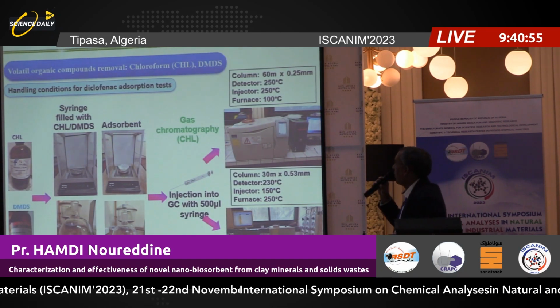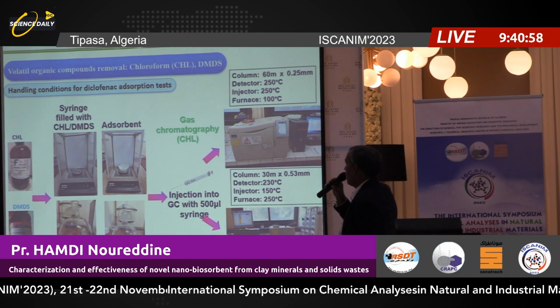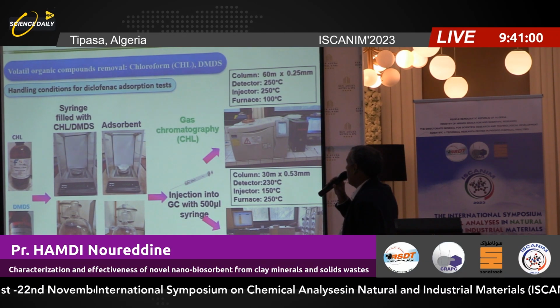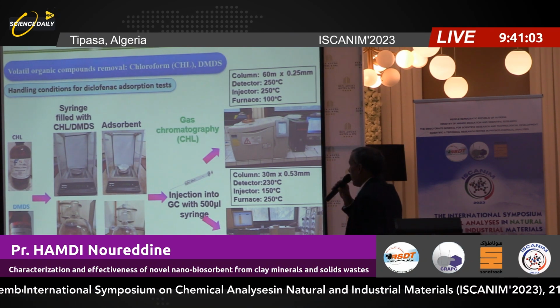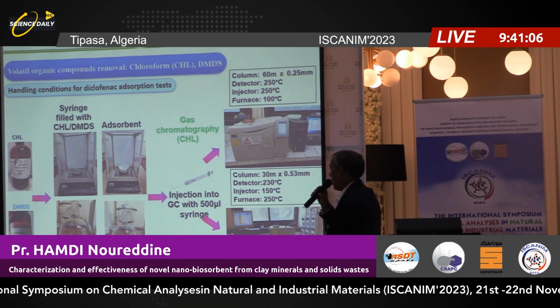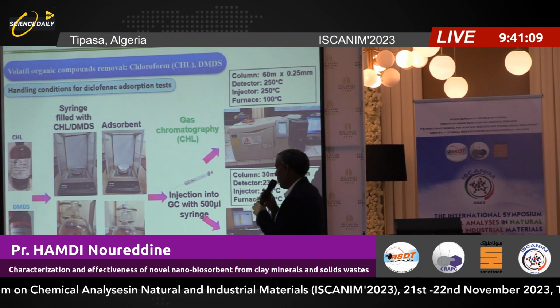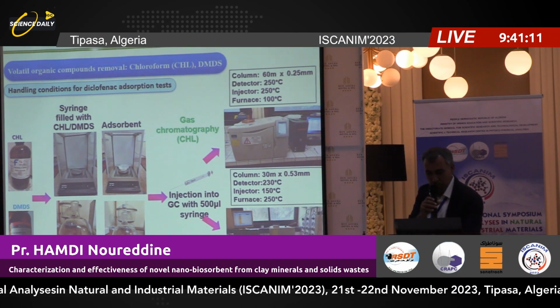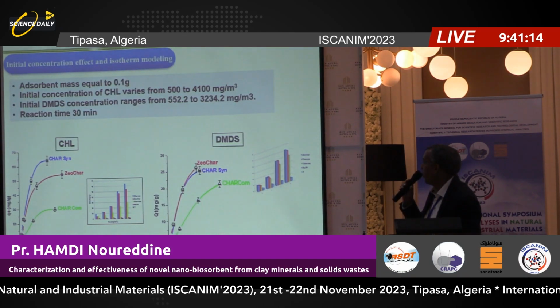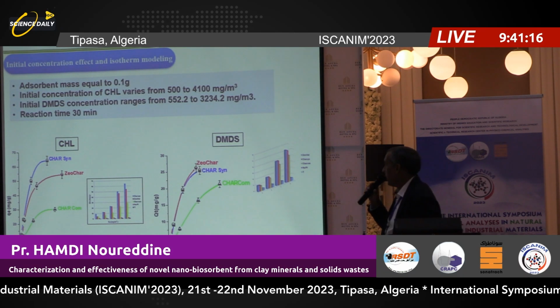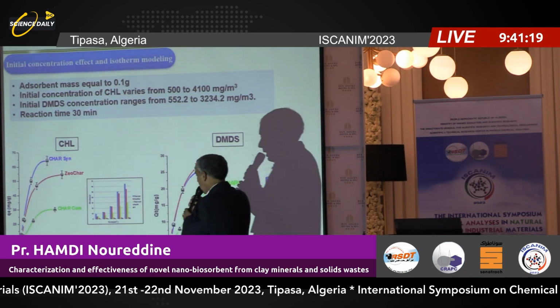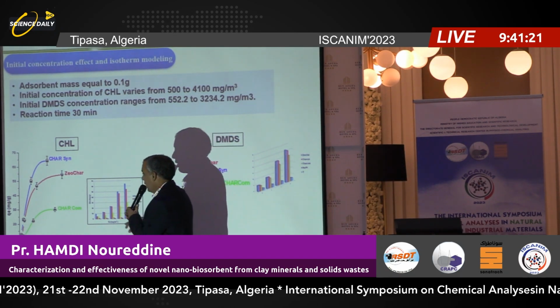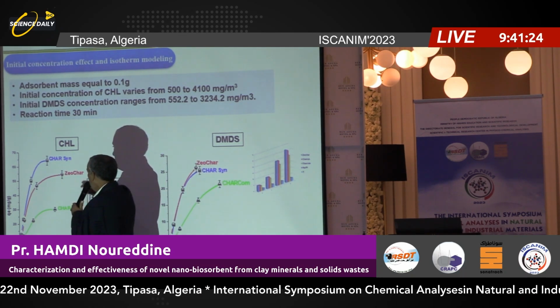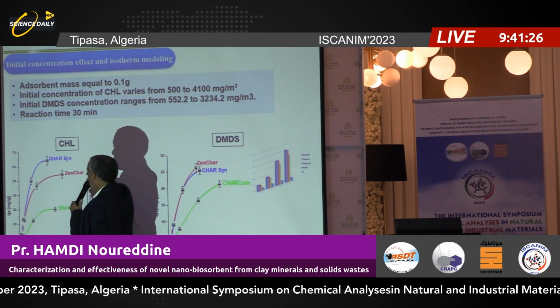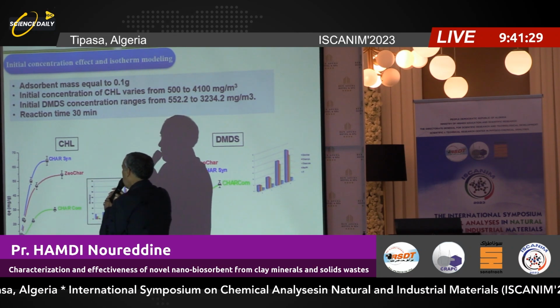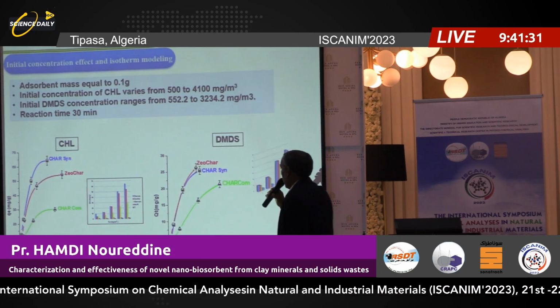We move to the adsorption of the volatile organic compounds, chloroform and DMDS, using characterization by gas chromatography, using a syringe with a volume of 500 microliters. The adsorption isotherm compared to the zeolite in this case: this is the zeolite, this is commercial carbon, this is the composite zeolite activated carbon, and this is activated carbon synthesized from the wood.